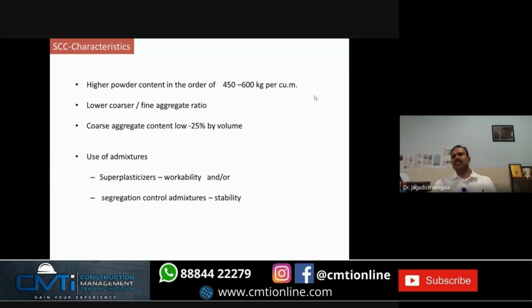In case of normal concrete, if you take a typical mix of 1 to 4, I cannot say, because all our design mixes we follow at the site. Say if you take a typical M20 grade of concrete, the coarse aggregate is approximately 1100, 1200 depending on the mix, and fine aggregate is around 700, 800 kgs. But in self-compacting concrete, you have a lower or equal coarse to fine aggregate ratio. What does that mean? In the last case I told 1100 plus 800, around 1900 kgs of aggregate in a concrete of 2400 kg.